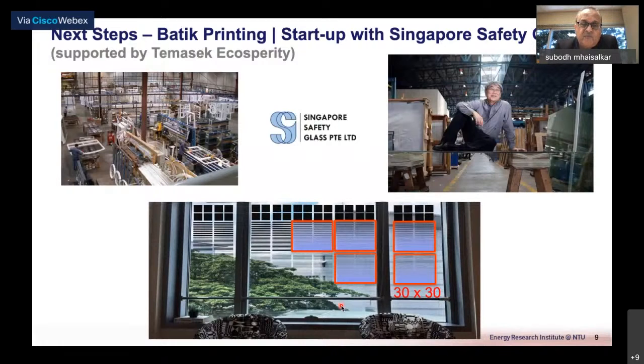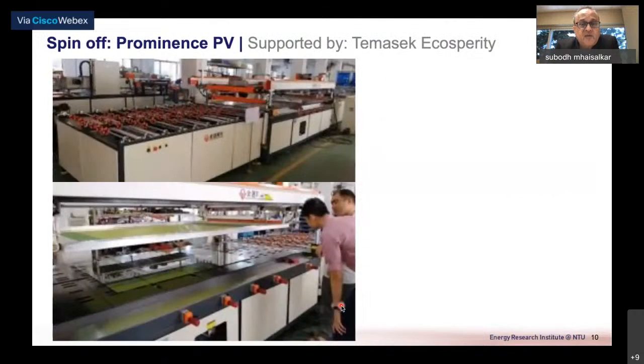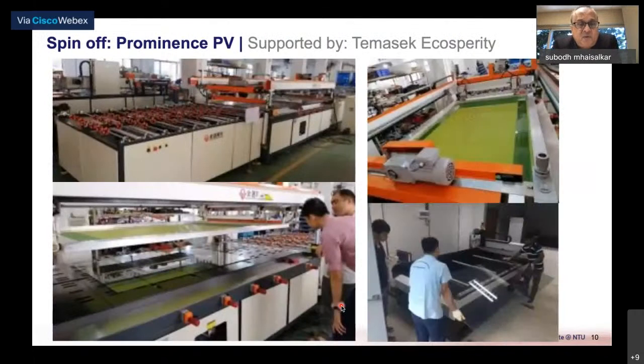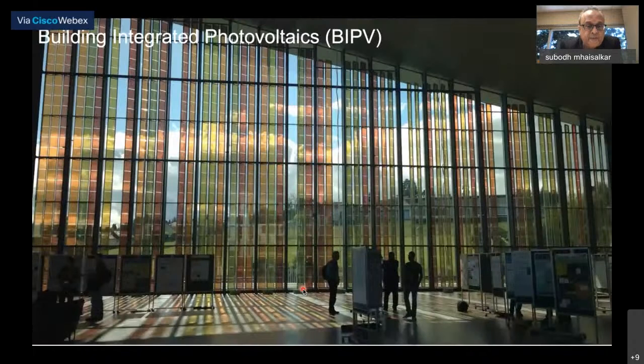So these are not really transparent, but as I said, I'll touch upon that later on as well. Some of the things that we are venturing into is deposition of perovskites over, as you can see on the panel in the bottom, a piece of glass which is 2 meters by 3 meters, and it takes 3 or 4 people to put the glass in place. And this is essentially our tools for screen printing, for laser scribing, cleaning, as well as processing of perovskite window glass. So these are the kind of work that is ongoing.